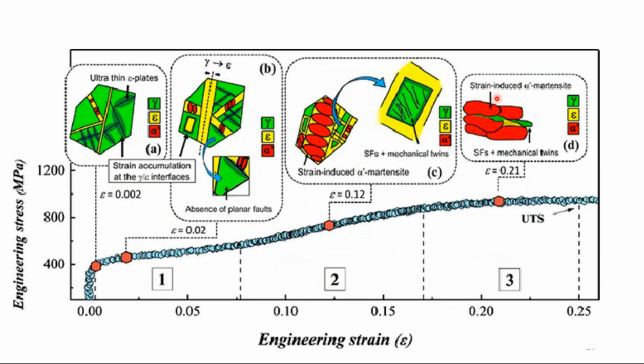And for complete research, again, you can go to the paper and analyze all the beautiful pictures they get, and they correlate this information from the synchrotron with the microstructure evolution. You can see a lot of green here corresponding to the austenite, and some part of epsilon martensite, a little quantity of alpha prime martensite. And then you can see the evolution, this green becoming yellow and red, more red. And in the end, you can see that most of the matrix has transformed to alpha prime martensite. This is a nice example of the things you can reach with this type of facility.